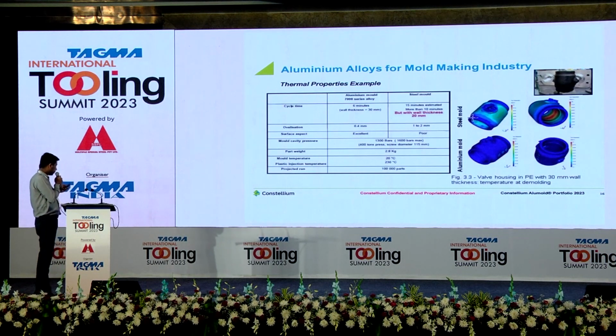This is a typical example of a thermal application. This is a valve housing in PE with a wall thickness of 30 mm. You can see the cycle time on the left-hand side with the aluminum series is 6 minutes, with a 30 mm wall thickness in aluminum alloy. In 20 mm wall thickness in steel, it has taken 15 minutes. It's more than 50%. And the ovalization is reduced from 2 mm to 0.4 mm. This is a cavity pressure of 1,300 bars and the maximum pressure of 1,600 bars.